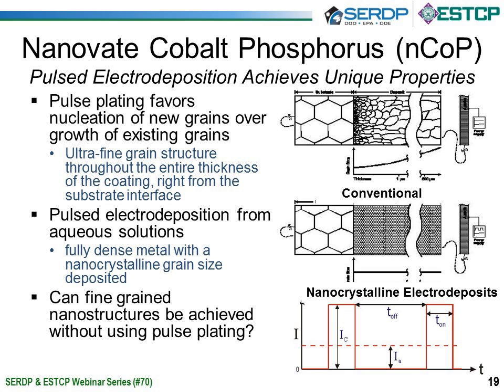And what that achieves is a very fine-grained uniform structure throughout the thickness of the coating. In conventional plating, typically you see a fine-grained structure right at the interface. However, as you grow to thicker structures, you commonly find the grains elongate to larger grain sizes. Through the use of pulse plating, you can favor the nucleation of new grains over the growth of existing grains, and this results in an ultrafine grain structure through the thickness of the coating.